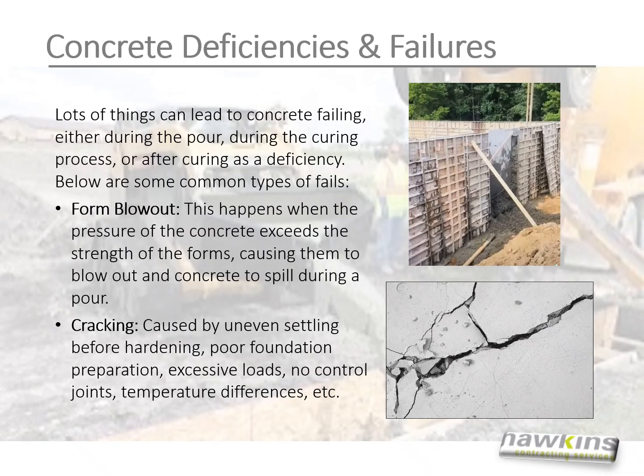Concrete deficiencies and failures. Lots of things can lead to concrete failing, either during the pour, during the curing process, or after curing as a deficiency. Below are some common types of fails. Form blowout. This happens when the pressure of the concrete exceeds the strength of the forms, causing them to blow out and concrete to spill during a pour. Cracking. Caused by uneven settling before hardening, poor foundation preparation, excessive loads, no control joints, temperature differences, etc.